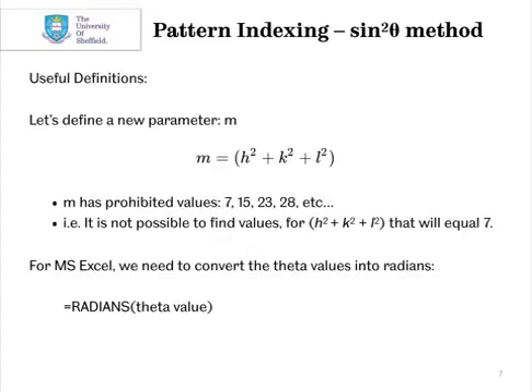Some other useful things that we can define. Let's make a new parameter m, and m is just going to be the sum of h squared plus k squared plus l squared. You'll notice that it's not possible to find values for certain combinations of h, k, and l that will give the particular values 7, 15, 23, 28. So if you have a 1, 0, 0, m would be 1, a 2, 0, 0, m would be 4. It's not possible to get a combination of h, k, and l that will give you m equals 7, for example. And this will be particularly important in a short while. The other thing to mention is that if you're going to do this in Excel, you need to convert your angular positions into radians, and you can do that by the equation on the screen here.